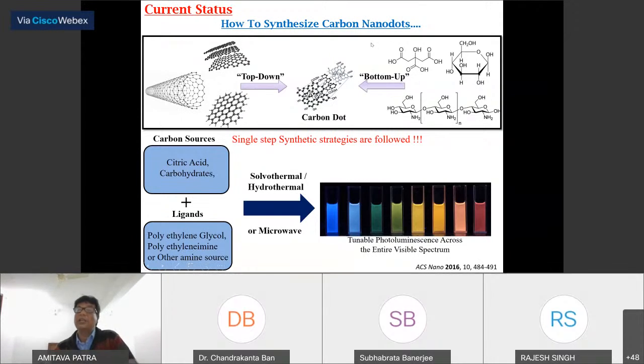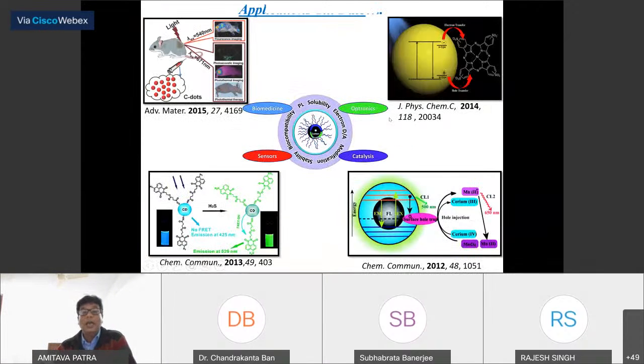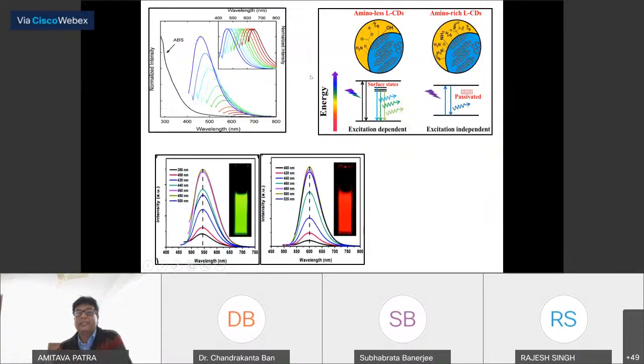Carbon dot is very interesting and obviously very difficult to understand. For those who are working in biology, there is no toxicity. That's why people develop different carbon dots, from blue to red, very simply from citric acid or glucose. You can use them for biological applications, for energy harvesting, for catalysis, and for sensing. This is not our work; this is our work for energy harvesting. But there are two important aspects here. One group of people are interested in developing excitation dependent emission bands, but a few people are interested in excitation independent emission. If you have a lot of defect structure in the carbon dot, then it could be excitation dependent. And if there is no defect structure, a very clean nanomaterial, then it is excitation independent.